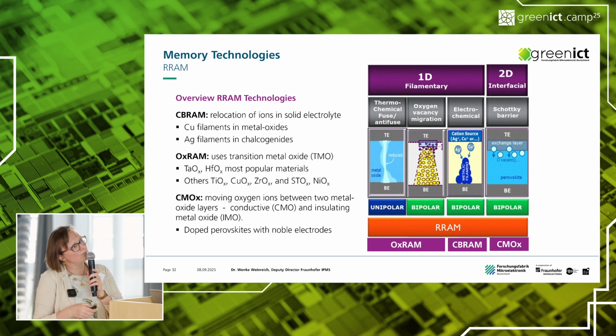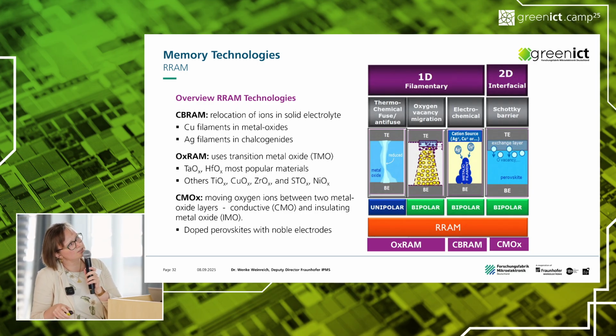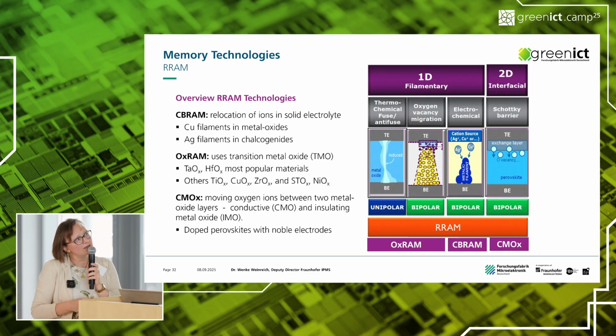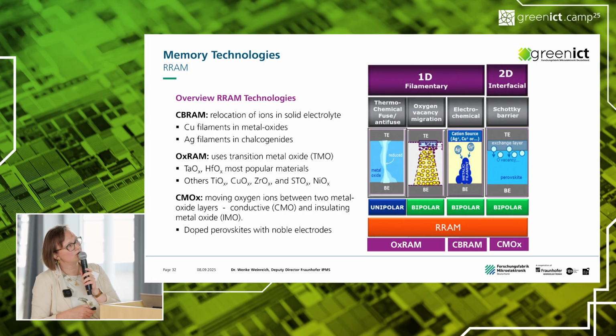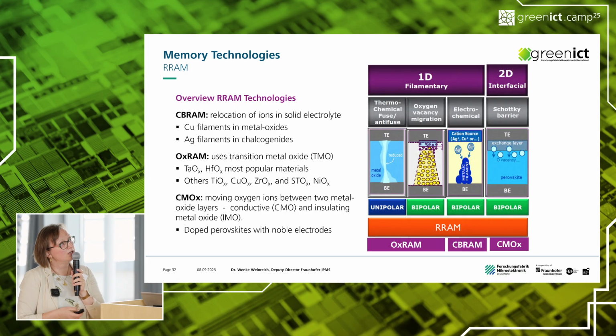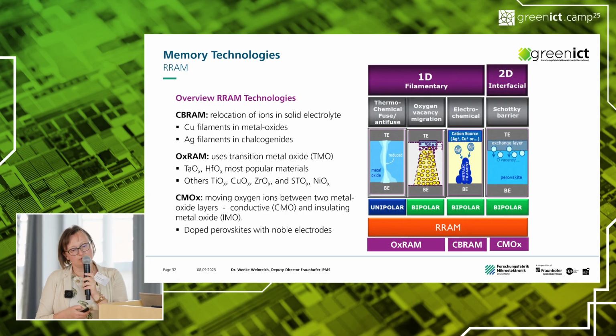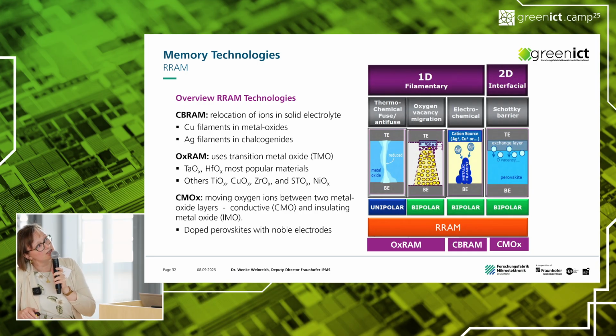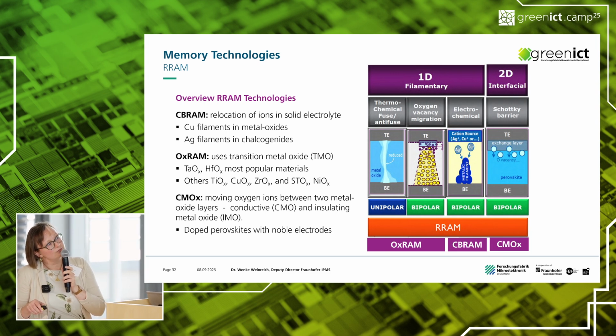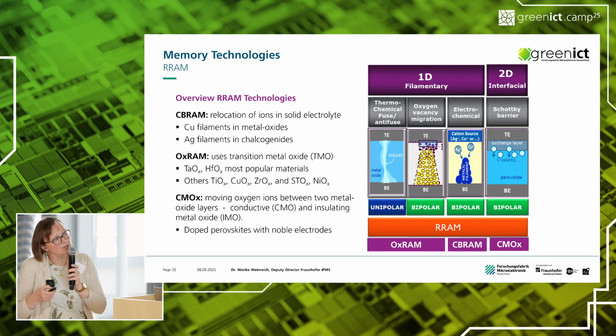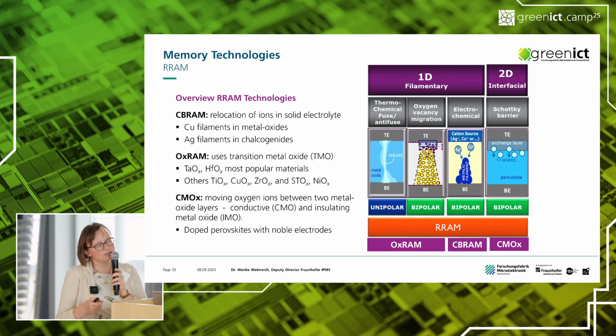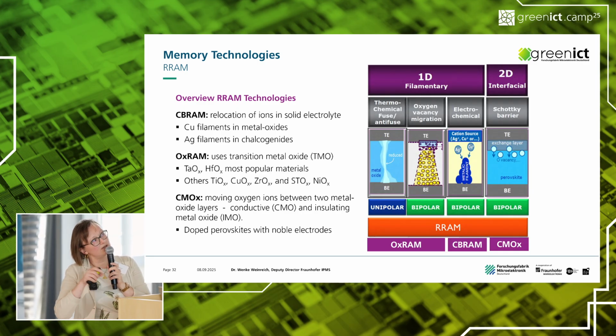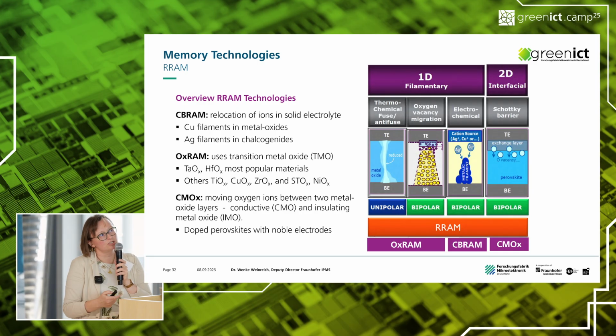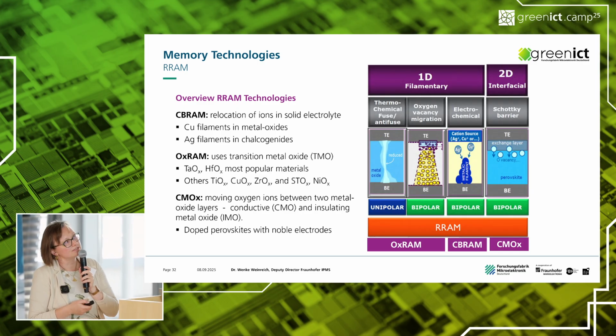The next version, which is more popular, is the so-called OxRAM. And here, maybe that is the most important one, you normally have a high-k material, that means a dielectric like tantalum oxide, hafnium oxide, also other materials. Inside these materials, you implement oxygen vacancies, and via these vacancies you make a filament through the material. If you have this filament, you have a conduction, that means a low resistance, and if it's broken somehow at one interface, then of course you don't have any conduction anymore, and you have your high resistance state.